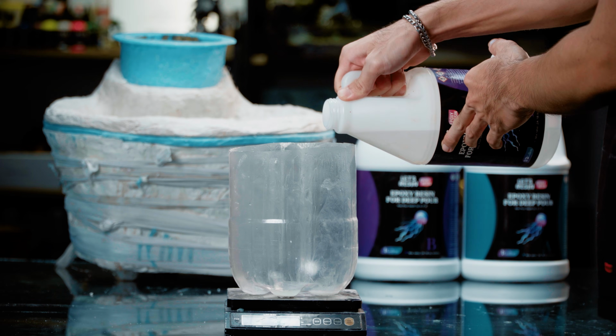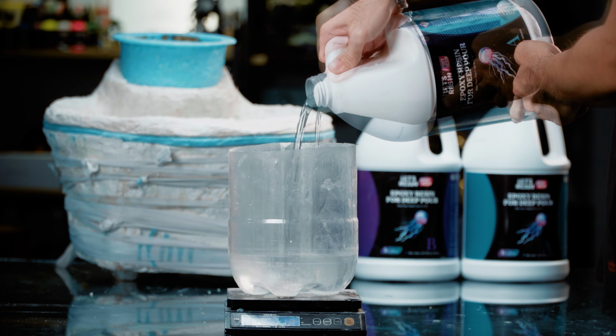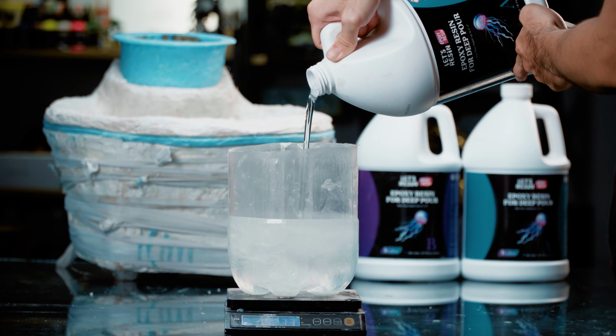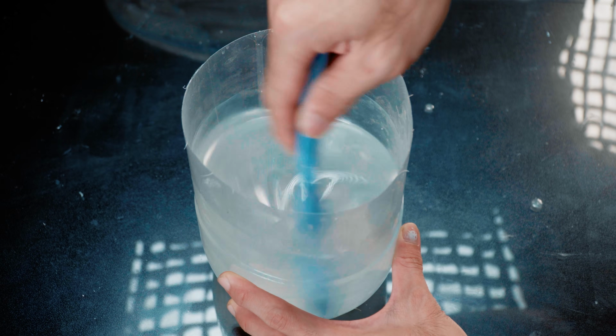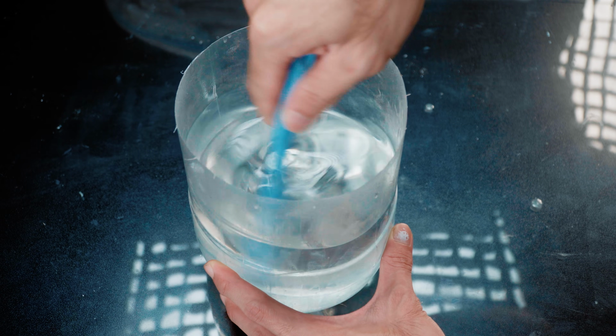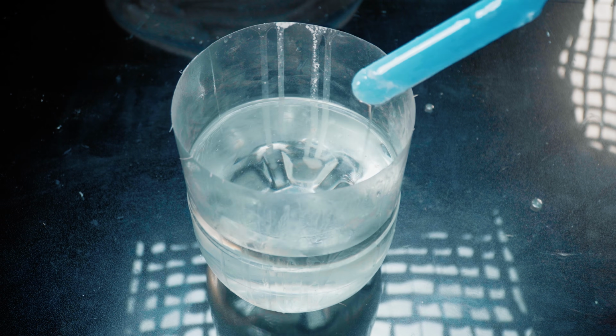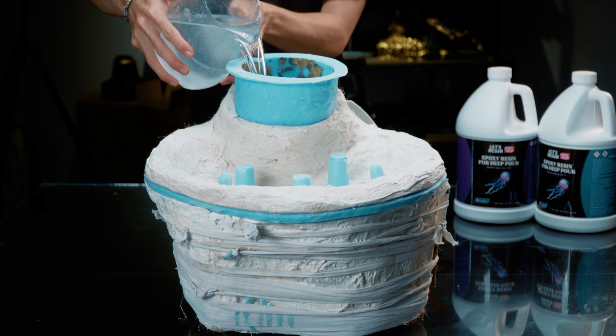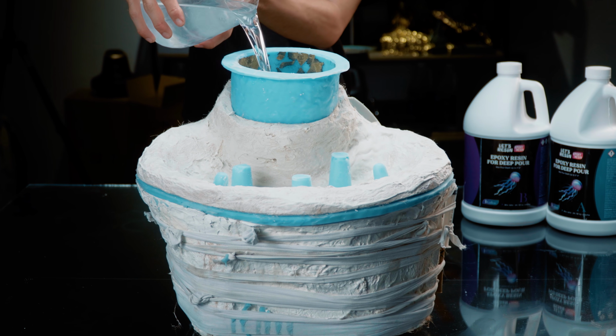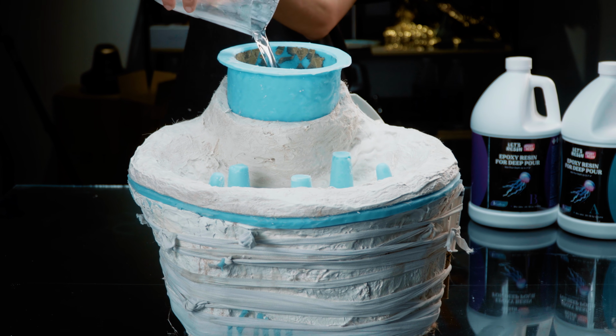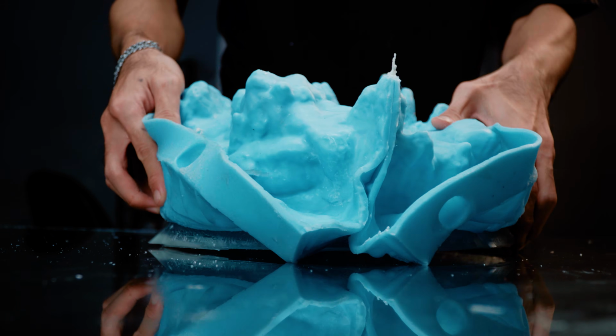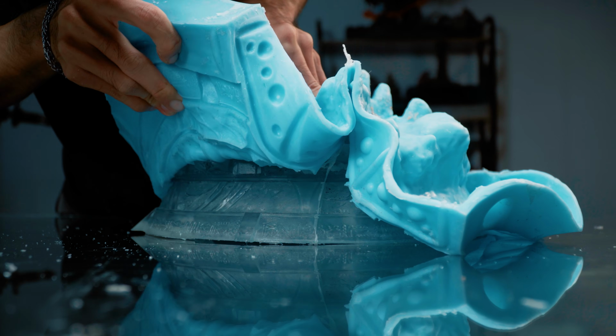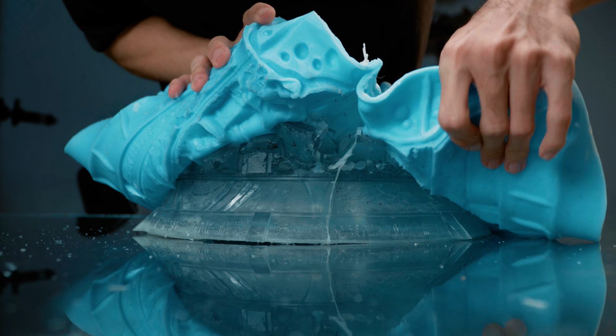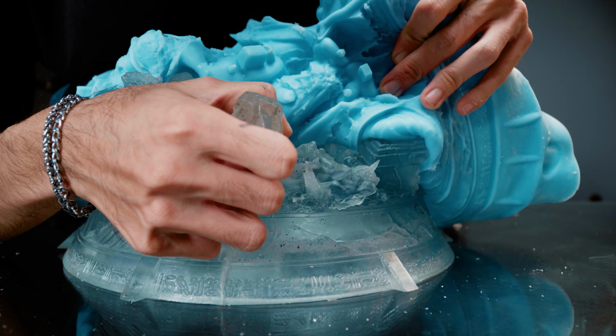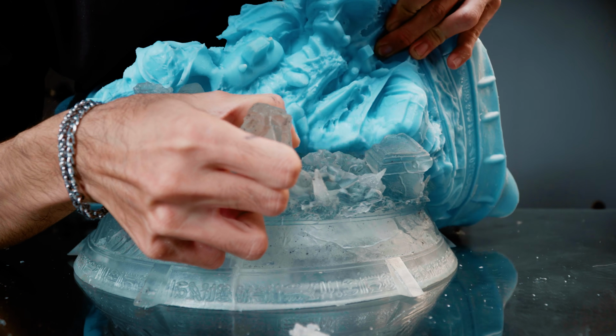I will mix 4 kilograms of epoxy resin to cast this diorama. With such a large amount of epoxy resin, it will only be safe to use Let's Resin's deep casting resin. With fast curing resins, the heat of 4 kilograms of reacting resin will be extremely large, which can completely cause cracking or yellowing. With the glue weight up to 4 kilograms in the closed mold, I could only breathe a sigh of relief when I removed the mold and saw the surface of the diorama that I had cast.